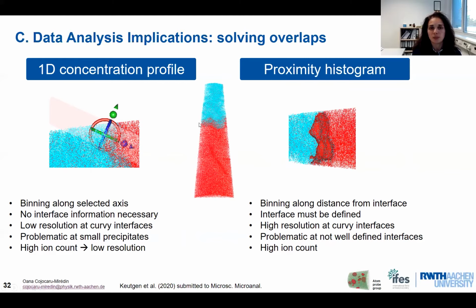So this method can be applied for 1D concentration profiles, where, of course, we don't care too much whether the interface is straight or curvy. We just want to find out how the elemental distribution takes place at the interface. In the case that we have a very curvy interface, and resolving the roughness of the interface starts to play a big role, then performing a proximity histogram really becomes very important. And therefore, we have implemented these methods for both the 1D concentration profile and the proximity histogram.